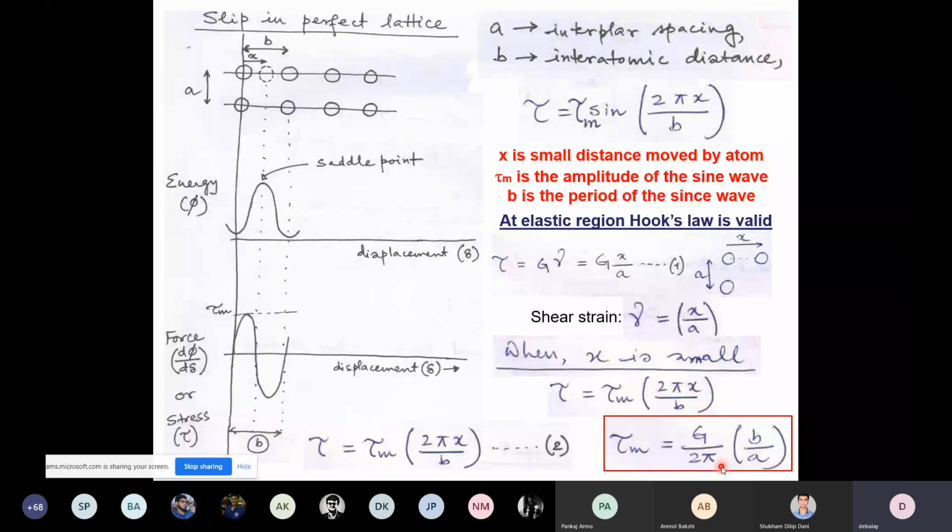So if it is a perfect, ideal, single crystal, defect free, you are supposed to get this much stress needed to create a dislocation and to cause a permanent deformation. That's why theoretical. But the actual value is much less than the theoretical. As we said, it comes down to G by something; you said that 13 GPa would be the value, but in structural steel, it is 300, 400 MPa yield strength.